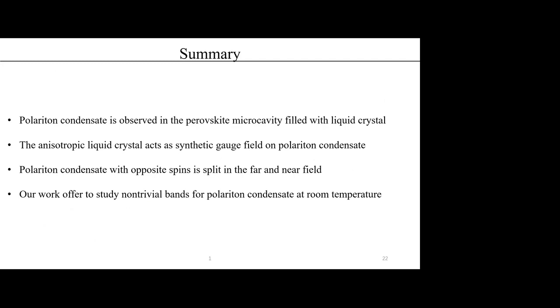Okay, to summarize, we realize exciton polariton condensation in our perovskite microcavity filled with liquid crystal at room temperature. This liquid crystal acts as a synthetic gauge field on the polariton condensate. Thus, the polariton condensate with opposite spins is split in both the far and near field. We believe our work offers a way to study non-trivial bands for polariton condensates at room temperature in the future.